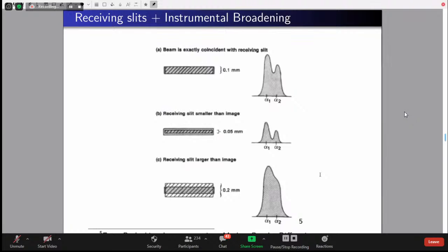People, whoever has worked, all that will become one single peak. And people think that it is because of the small crystallite size. I have a nanocrystalline zinc oxide. It is not true. It is because of the diffractionist, whoever is measuring, he has used a large receiving slit on the detector side. So how can we control this?